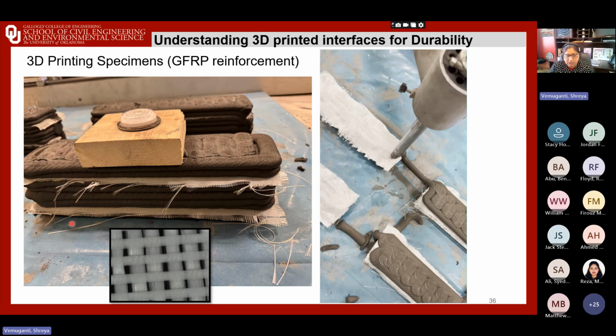You see that the bottom second interface and the top second interface are where we place these reinforcements. We use the spirit level to see if there is any inclination that we are looking at. So far, we've not seen any major inclinations. This is the glass fiber reinforced polymer mesh, and you see those mesh opening sizes as well. When we look at this continuous reinforcement printing, these interfaces, you see that they remain visible. And they are potentially those permeable interfaces, but we can learn more when we look at those observations.